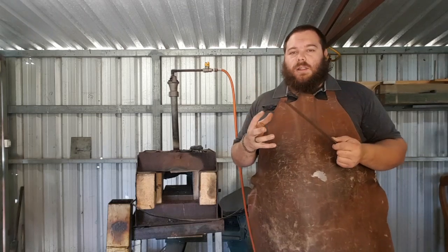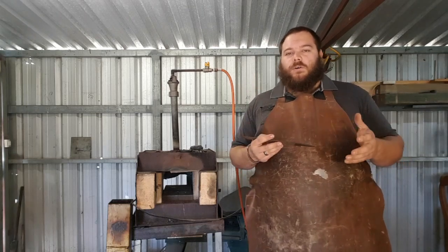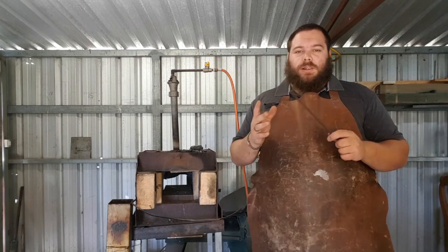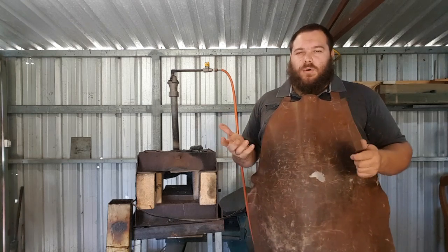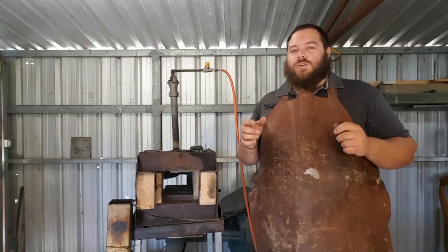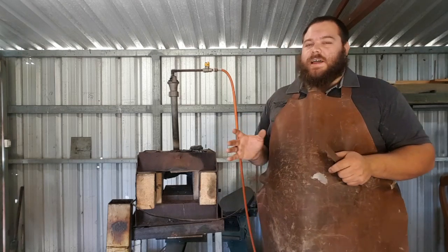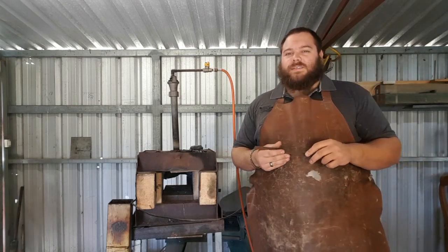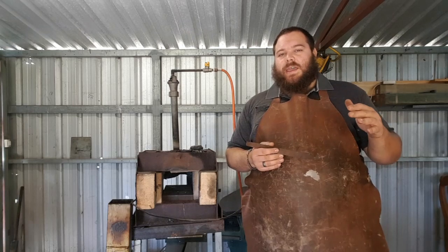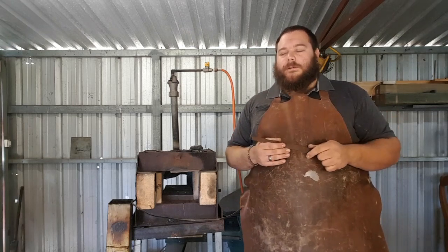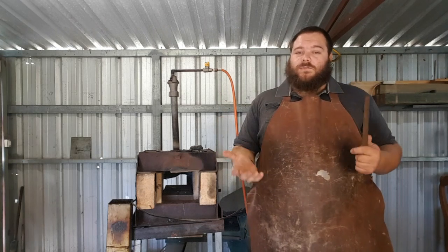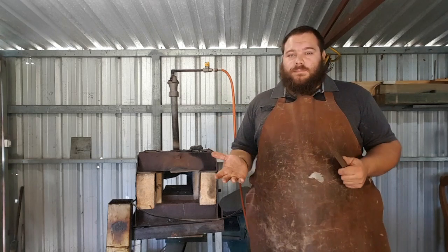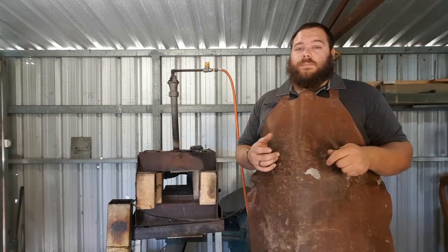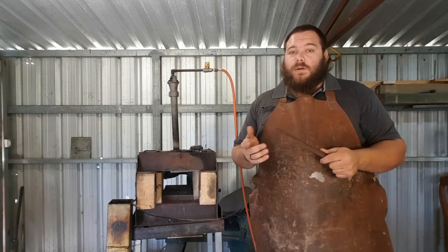But the very basics that you need for a hardenable steel is an iron piece with a carbon alloy of at least 0.4%. You can harden things below 0.4%, to about 0.25%, to a very, very slight degree, but 0.4% is basically the bare minimum that I would say is required for hardenability. That's what I normally use for my hammers. I use chromoly steel, which is 4140, 41 being the chromium, and then 40 being the percentage of carbon, 0.4.